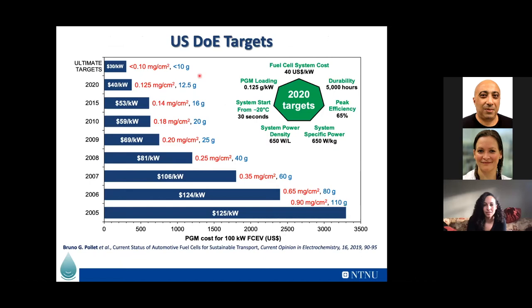Again, here, if you look at the DOE target, that was actually last year, the 2020 targets, we're looking at pretty much 10 grams of total loading of platinum. These days, with a loading of about 0.1 milligram per square centimeter, that would be the target at a cost of around $30 per kilowatt. So as you can see, over the years there has been quite substantial work in reducing the amount of platinum by a factor of 10-ish over 15, 16 years. So that's a good job that's been undertaken.